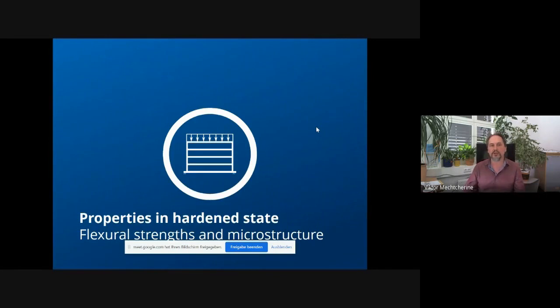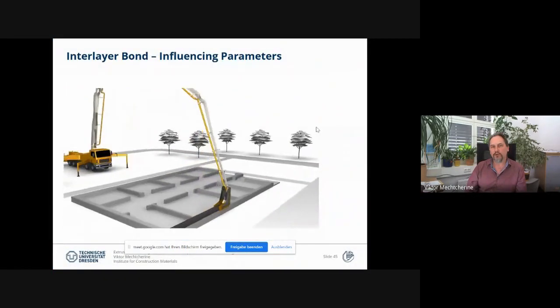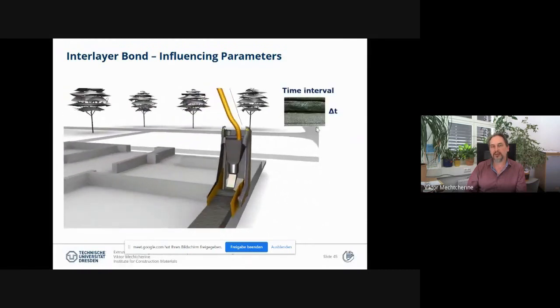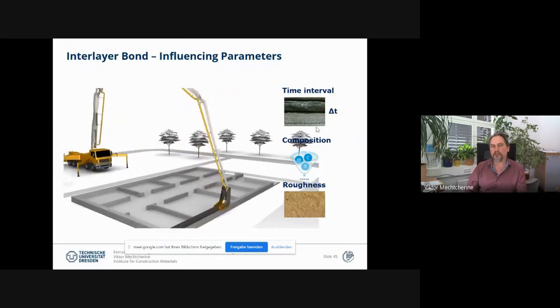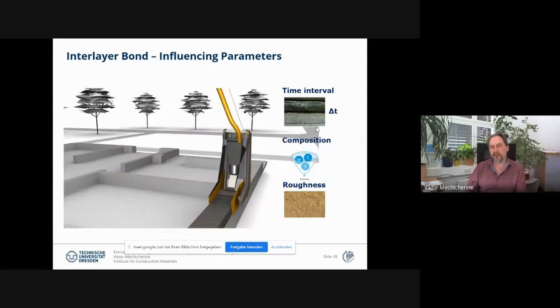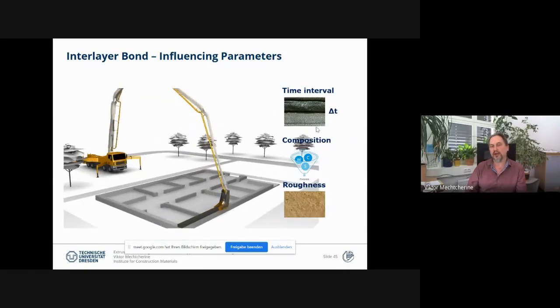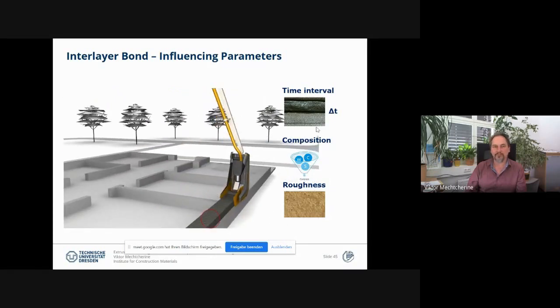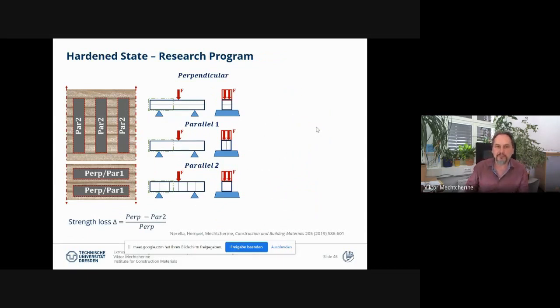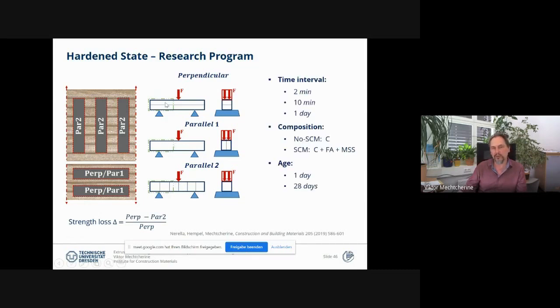So let me say also a few words on properties of print concrete in the hardened state. We have here, first of all, the effect of the time intervals, the concrete composition, and the roughness of the surface on the interlayer bond. And the interlayer bond affects to a great extent the degree of heterogeneity and also a possible anisotropy of the material. So we studied this phenomenon by cutting prisms out of the wall in different directions and testing them in different directions. Of course, you can expect some effect of these layers depending on the orientation of the layer relative to the force we apply. And you see the parameters under investigation: the time interval, composition, and the age of the concrete element.